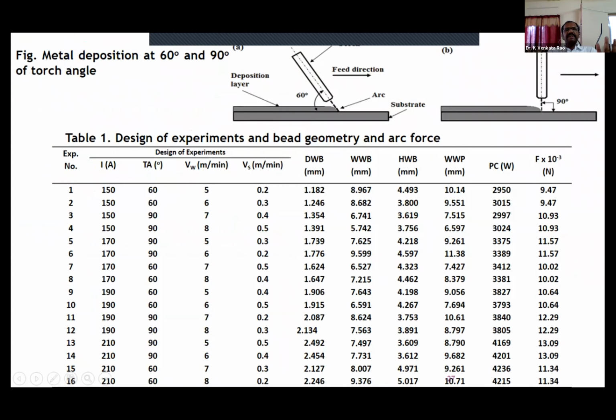So 4 welding speeds, and VW is the wire feed speed. Sorry, VW is the wire feed speed. Third one is wire feed speed 5, 6, 7. VS is the welding speed 0.2, 0.3, 0.4, 0.5 meters per minute. So after performing this experiment, the workpiece was taken out.